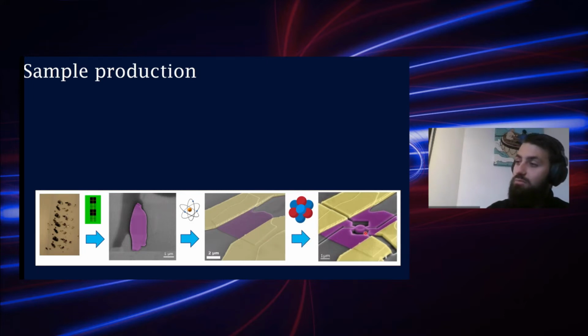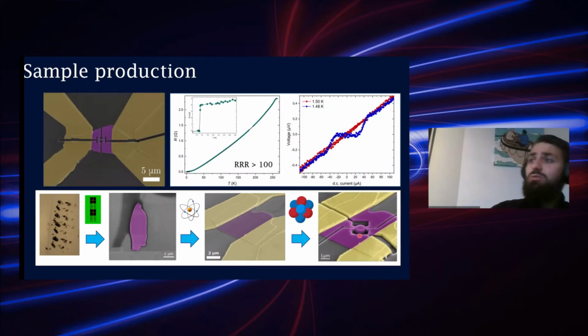And next we do focused ion beam milling to mill these crystal flakes into microstructures of all shapes and sizes. Focused ion beam milling is often considered a quite violent method. However, if you do it the right way, you don't have to sacrifice sample quality at all, which is shown here, since if we cool down one of our crystal flakes, we often see very high residual resistivity ratios for our smallest structures above 100, and for the micrometer-sized ones, often above 300, with very, very sharp transitions at 1.5 Kelvin. As you can see here, only 20 millikelvin makes a world of difference. So the transition is quite sharp indeed.